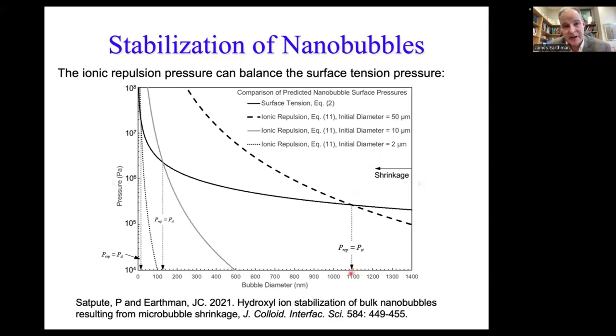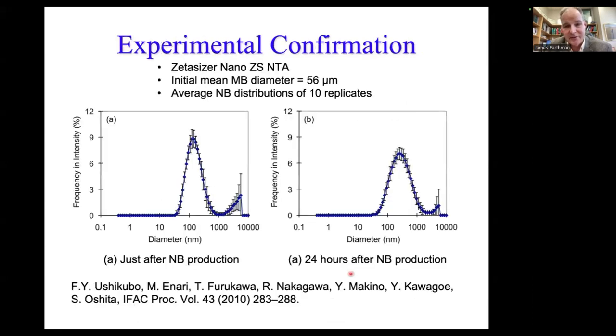Okay? So first thing I wanted to do when we saw this is see if there was any experimental data to confirm this, and it turns out there is. This is some data from a group in Japan who did zeta sizer nano measurements. This is a light scattering technique. They could measure the zeta potential. They could also measure the size of the nanobubbles with this instrument. And it's a light scattering method. It uses a CCD camera.